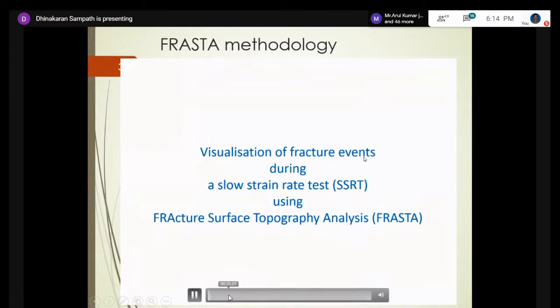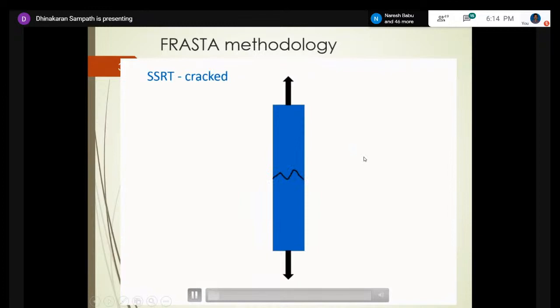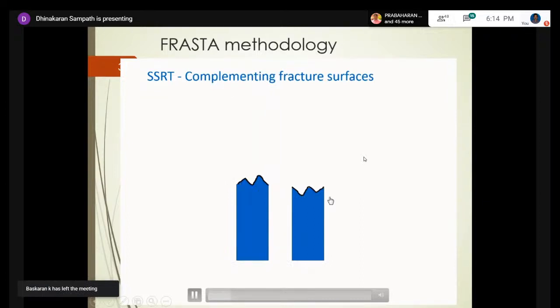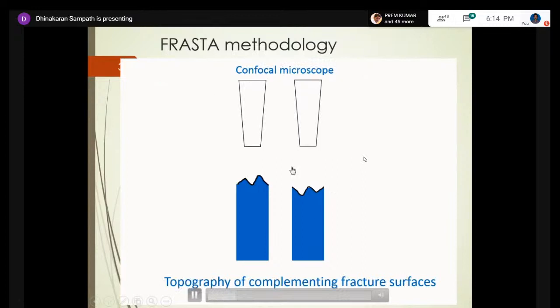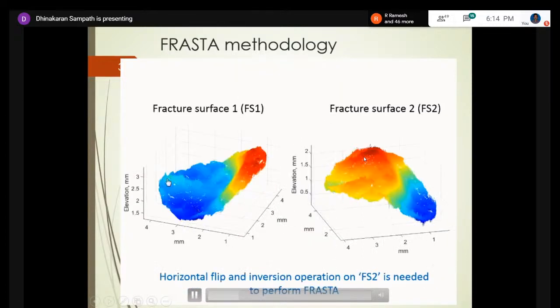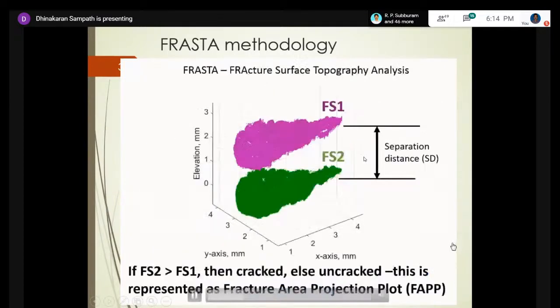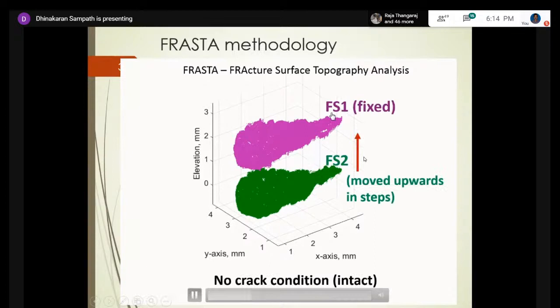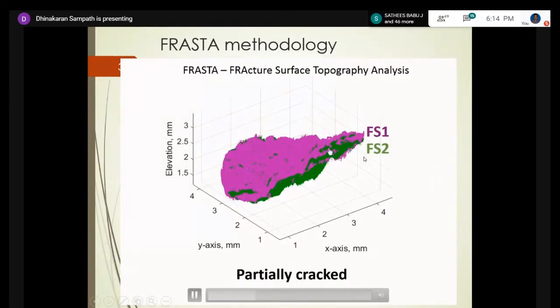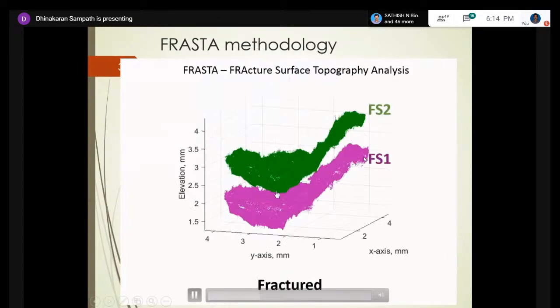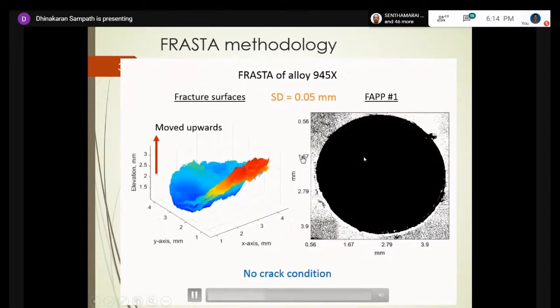So here I'm going to show the video. This is the slow strain rate test, and we have got a crack, then fractured, and these are the complementary fracture surfaces. We use a confocal microscope, which will give the depth data. That's what we call topography, and these are the topographs of the complementing surfaces. And this is the separation distance. So if FS2 is brought down and moved up slowly, at the minute it is partially cracked, it is moving up. Some places we see that it is coming out. So now it's fractured. We use this in small steps to get the crack evolution in multiple steps.